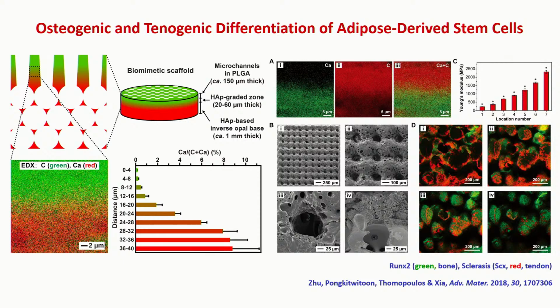And the top layer is going to be patterned using micromachining. In the IEN, they have this nice capability to machine these arrayed channels into this film. At that time, we only had this CO2 laser, so the precision and capability was not perfect. But you do get a pretty small size, about 100 micrometers. But the surface will become very rough. This could be improved now by using a different type of laser, but at that time, this was pretty rough. This was the top surface, and this is the cross section I've shown over here. This is going to be the pores in this inverse opal scaffold.